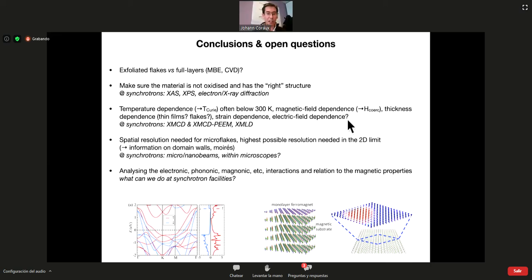Thank you. We have one question. The question is, what is the maximum thickness of the 2D chromium telluride film we are looking at for the optimal sample functionality? So the minimum thickness or the maximum thickness? I mean, the maximum, it can be very thick, but the minimum thickness, we have the feeling now that down to 4, 5, 6 nanometers, the system is still in plane magnetized and at room temperature, Curie temperature.